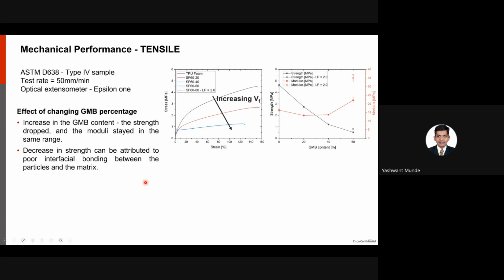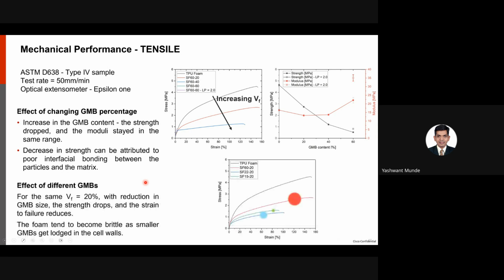The strength drop is attributed to poor interfacial bonding. We did not do any surface treatment before we printed these. These were as-received particles. So it's expected that in tension, it would not perform so great.